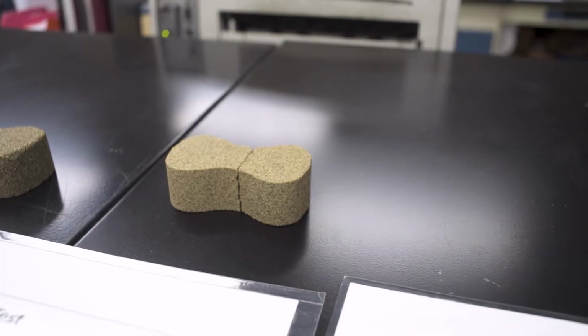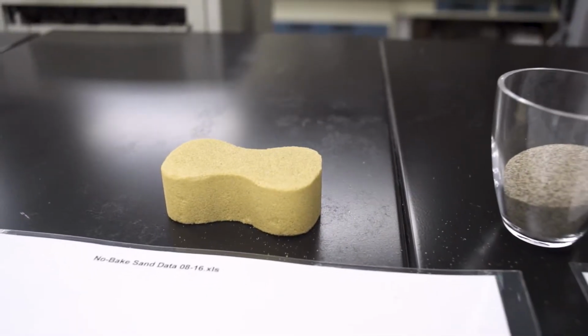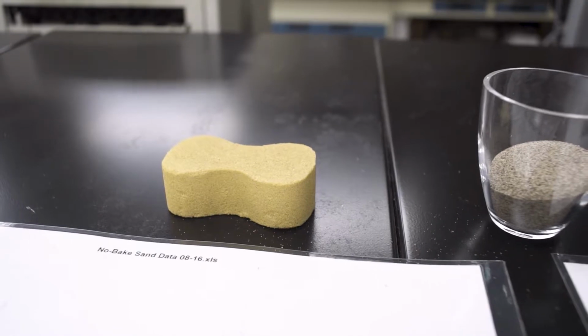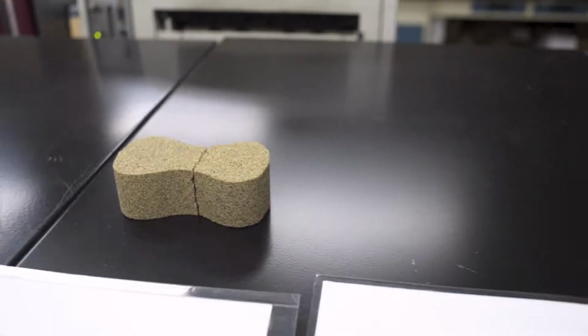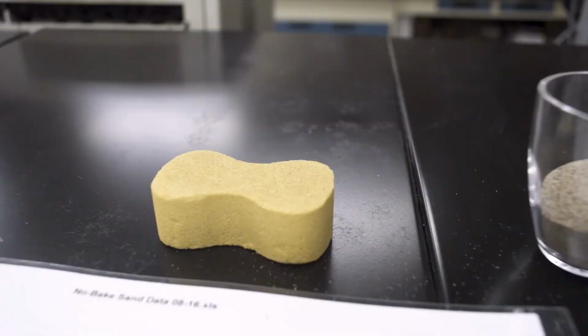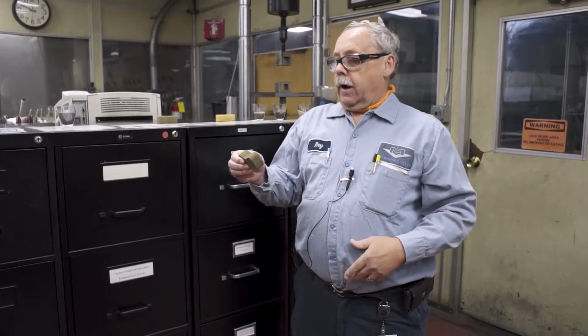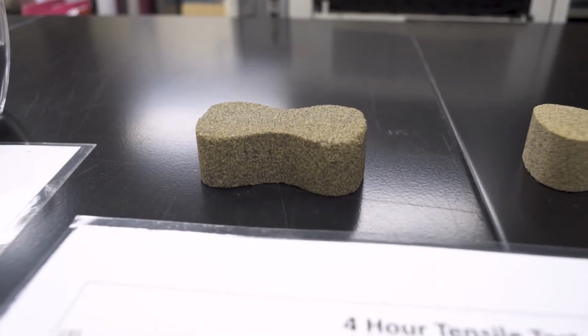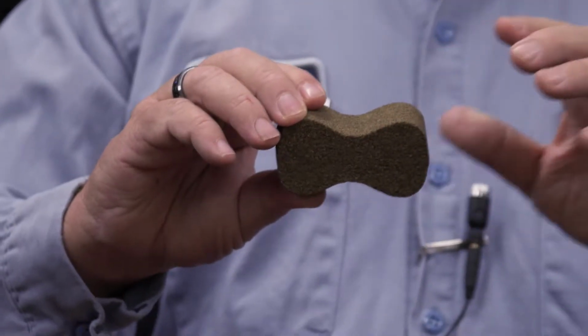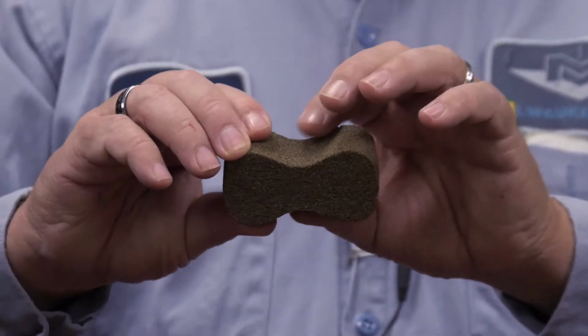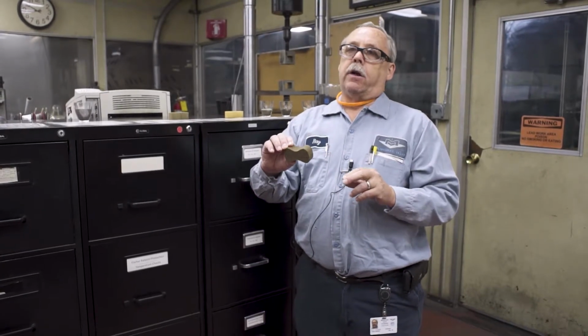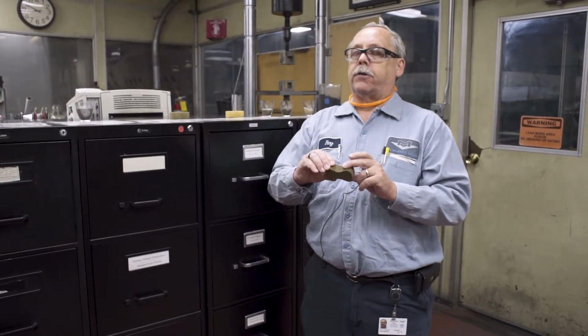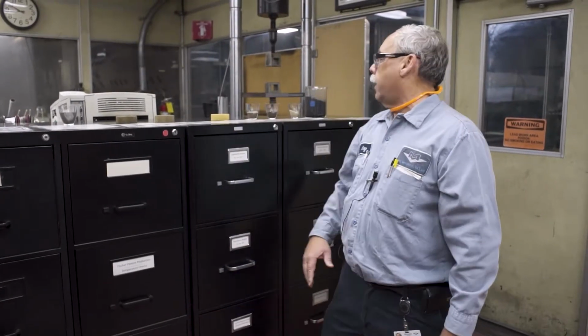We also have a no-bake molding line, which I'll be showing you later. That's a molding line that has a sand, it's again silica sand. It's mixed with 2 resins, and then we have a catalyst that activates it and hardens it. It'll harden it into a very hard piece for molding. This here happens to be what we call a dog bone. We make these dog bones regularly during the day, and we'll pull them at 1 hour, at 4 hours, and at 24 hours. And we monitor that tensile strength on those molds, because it's critical.